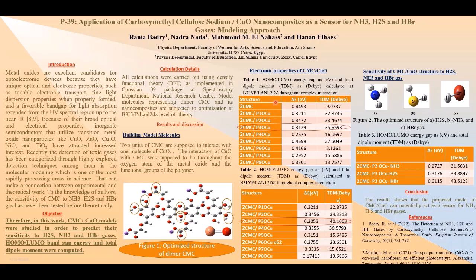As we can see from Table 1, the total dipole moment of the complex interaction increases by changing the position of the interaction. Meanwhile, HOMO-LUMO band gap energy values change by changing the position of the interaction. We see that the position named P3 has the highest total dipole moment and the lowest HOMO-LUMO band gap energy. Meanwhile, for the adsorbed interaction, we observe the same sequence: the total dipole moment changes by changing the interaction site, and the HOMO-LUMO band gap energy also changes.